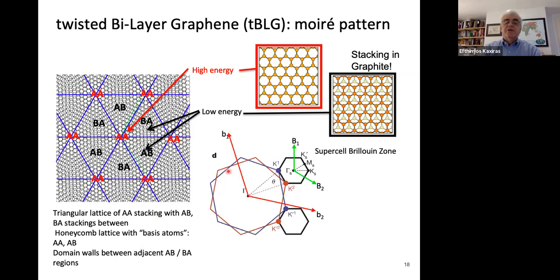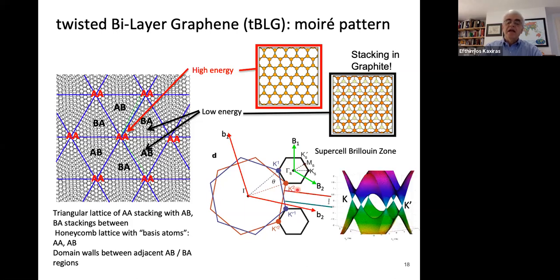And here are the Brillouin zones of the bilayer system. So you get a Brillouin zone from one layer, the blue one, and another Brillouin zone from the other layer, the red one, twisted relative to each other. And the arrangement introduces this supercell Brillouin zone. So this basically corresponds to the periodicity, if you are dealing with a periodic system, of the supercell. And now, related to each one of these large Brillouin zones is a set of Dirac cones. So there's a Dirac cone from each layer at these corners of the supercell Brillouin zone. So that's what we have to deal with in a twisted bilayer graphene.